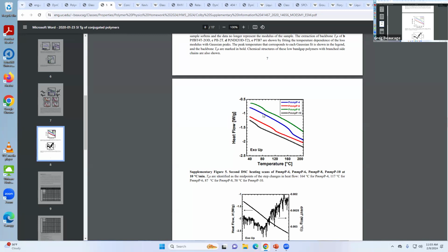So it should go, and this is negative heat here, right? So it's going down because it's negative heat. And then you should expect to see it take a dive when you get to the liquid state, right? And that cutoff point will be the glass transition. But because it involves motion, it depends on how fast you move this, and there's going to be an overshoot. So you overshoot that crossover point, and that causes this kind of knee. But the slope here will be the heat capacity of the glass, and the slope here is the heat capacity of the liquid, and the in between would be the glass transition. They usually take that other sigmoidal thing, the middle of that, as the glass transition for a DSC measurement.